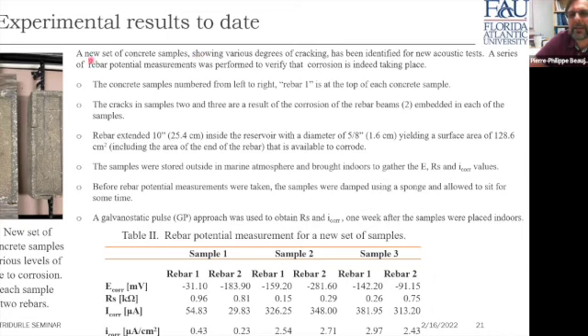So here's the thing, this new set of concrete samples showing various degrees of cracking have been identified and are currently used, and a series of rebar potential measurements have been performed to verify that corrosion is indeed taking place. Now the concrete samples are numbered from left to right as sample 1, 2, and 3. And in each sample, the top rebar is rebar 1, and the bottom rebar is rebar number 2.